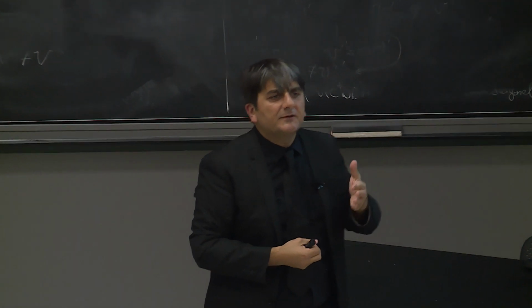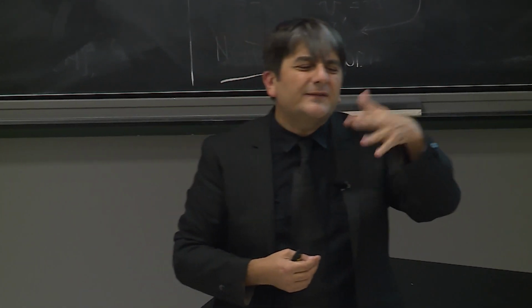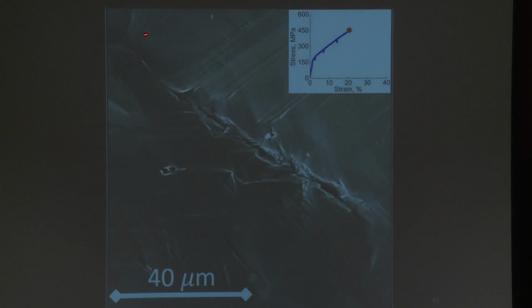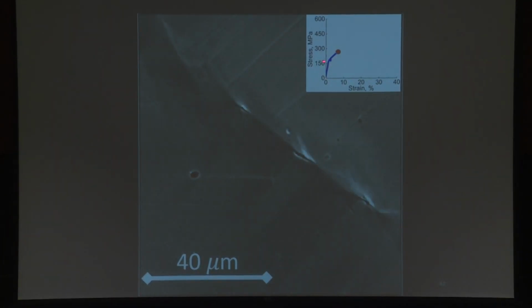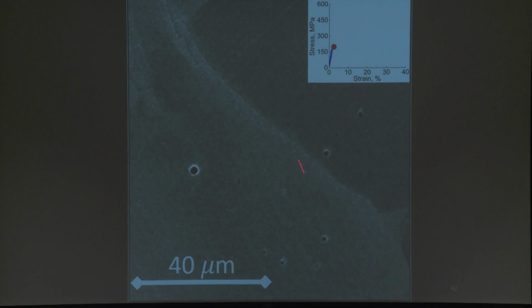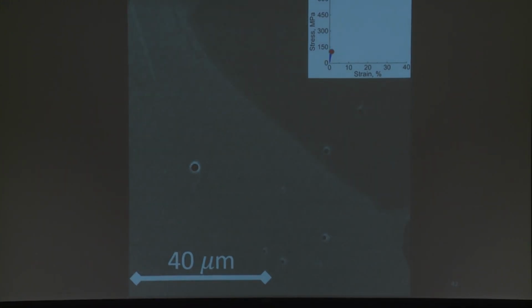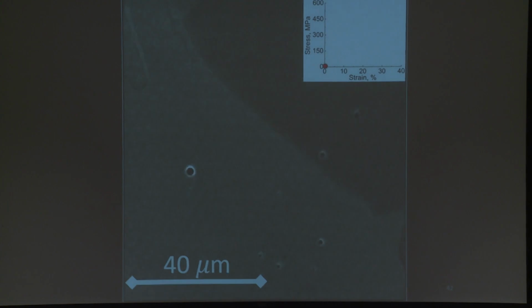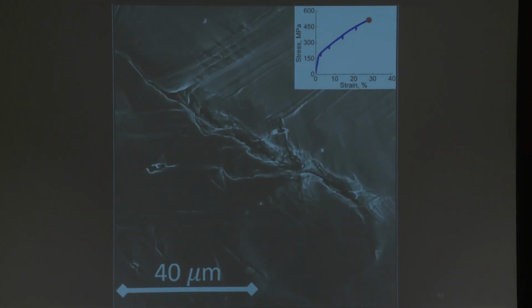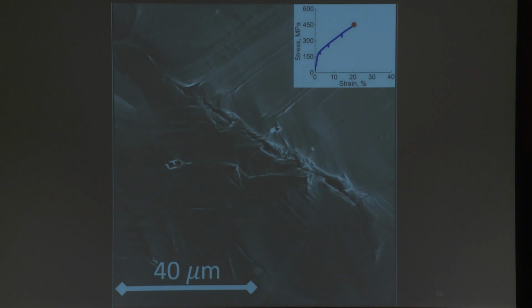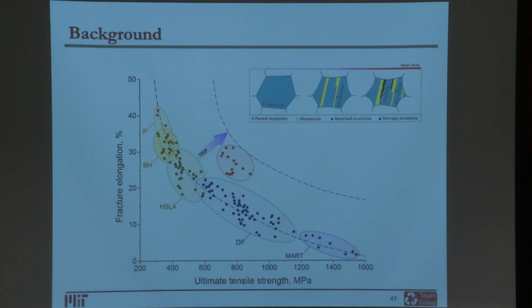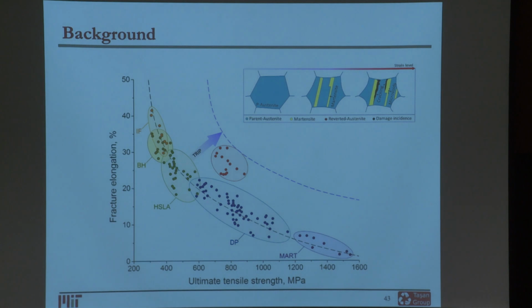So it's a funny situation a bit. You want a transformation, but you don't necessarily want the end product. And you can see this in this nice movie from Shalu's research, where you are deforming a material and you get this nice strain hardening response, but that's quickly followed by damage nucleation at this boundary because of the martensitic transformation taking place. So it's a strange situation. You want the transformation, you want the end product, but it's also the end of the material in a way, by causing damage upon further deformation. So how do we solve this? How do we still have the benefits of the transformation, but get rid of the problems that it's generating?